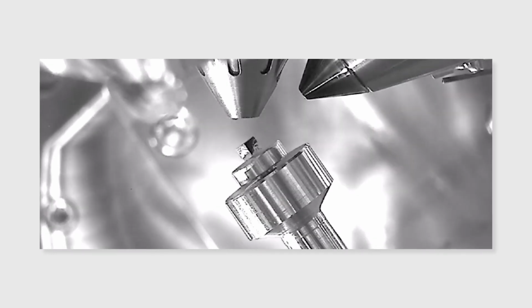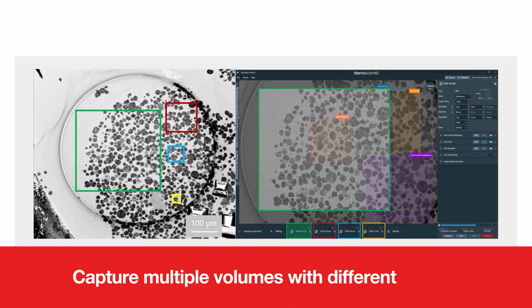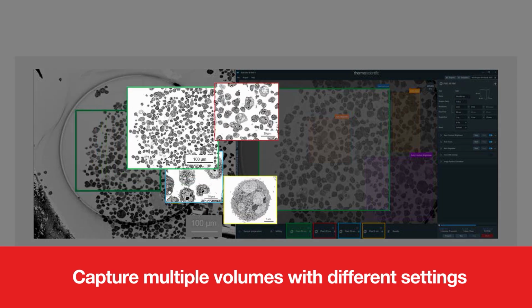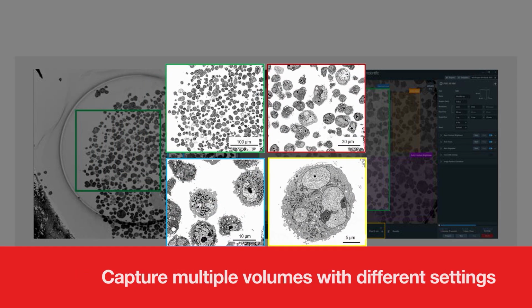I'm very often asked why spin milling. Coming back to the benefit of this approach, it's similar to what you might know from serial block face imaging. So you really remove the material and then image the sample, and you create again a stack of images that ultimately will serve for the reconstruction of the 3D volume. What is beneficial of having access to this large area is that you immediately can identify the sparse regions, which are the regions of interest and where you actually would like to record your volumes at high resolution.